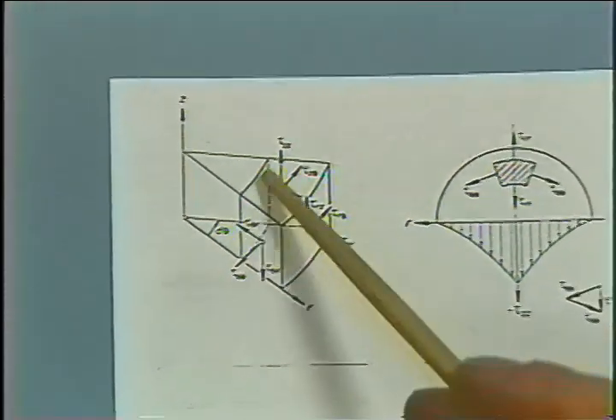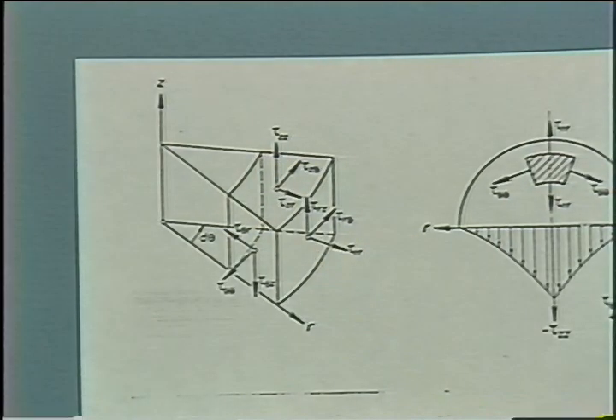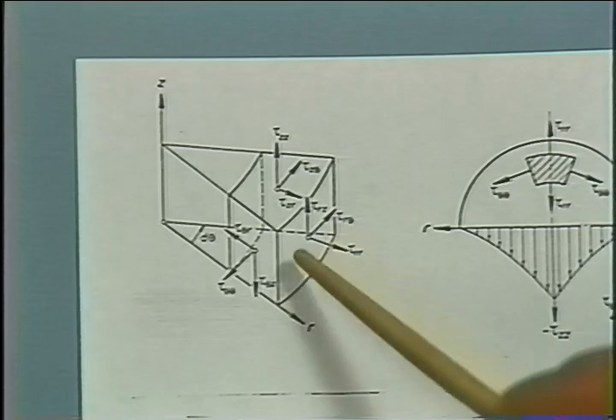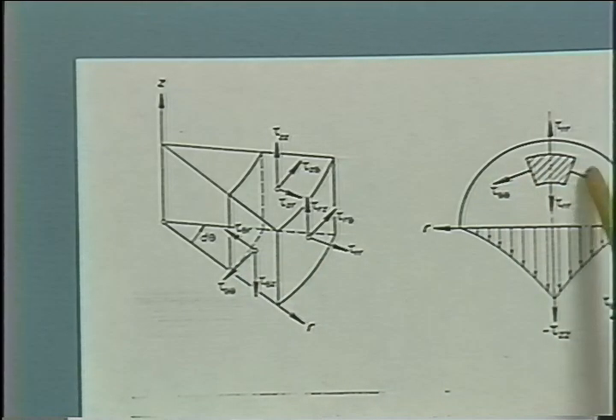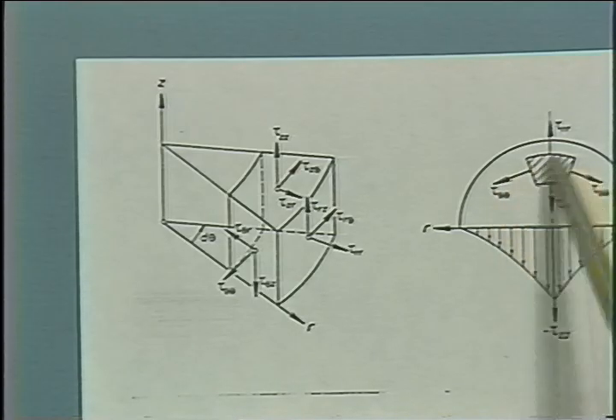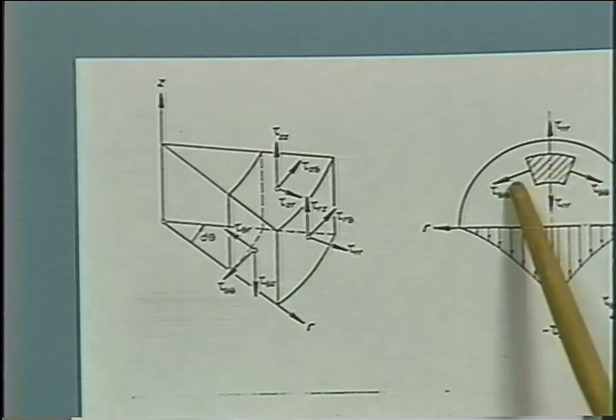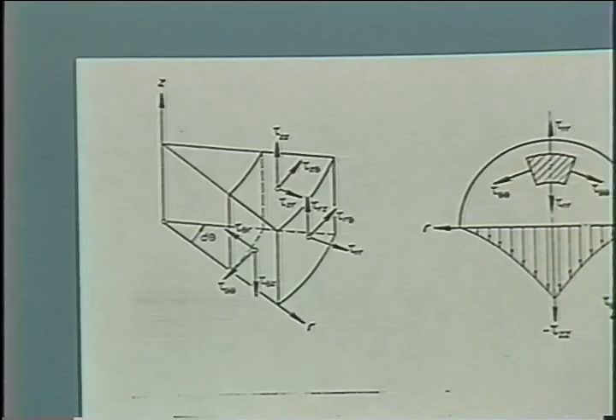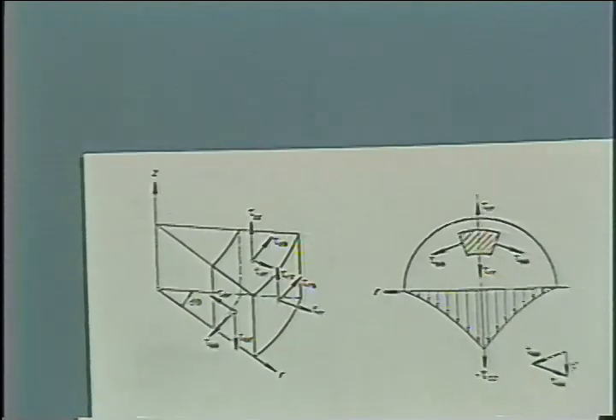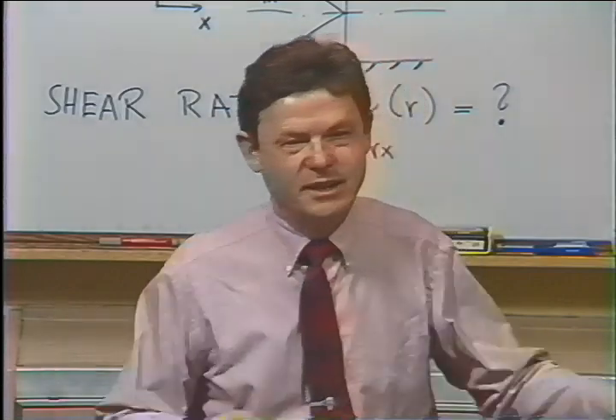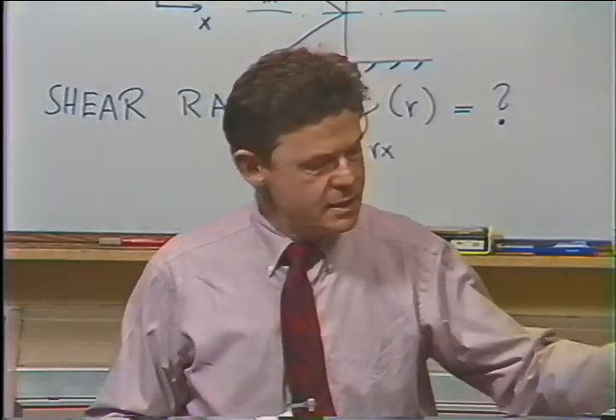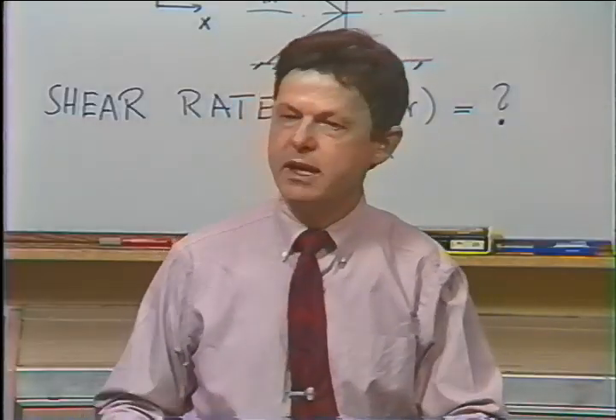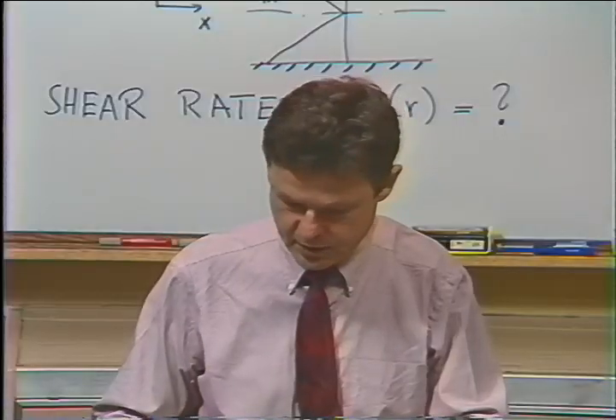Remember, the stress on a material element in the Couette flow geometry is drawn something like this. It's like a piece here, with this angular curvature effect. So the stress has a different direction on both sides, and that gives rise to tension in the circumferential direction. But this tension is of no interest if you choose a gap which is very, very small, if your whole flow reduces to plane flow. So if you want to have N1, you need a wide gap, but then you have to deal with the inhomogeneity of the kinematics and correct for that. The kinematics is analyzed very nicely in Bird, Armstrong, and Hassager, and in textbooks you'll find that. So I don't want to go into further detail.